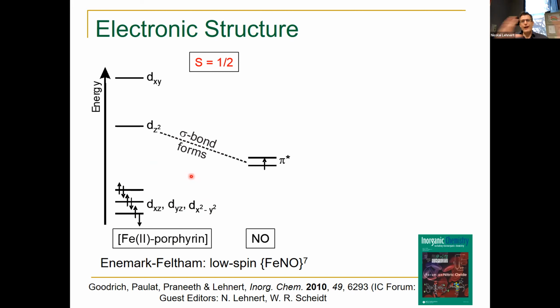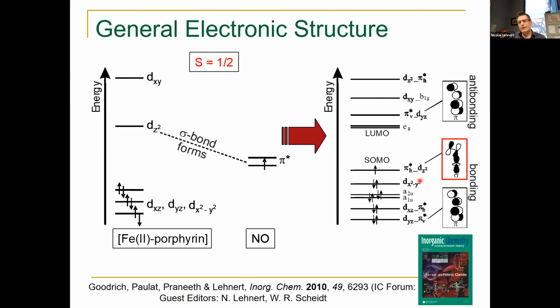So then, when we let these two fragments interact, we end up with this kind of a molecular orbital diagram. And the key orbital here is this interaction between the dz squared orbital of iron and this pi star orbital here of NO. This is a very covalent interaction. In the 5-coordinate complex, this is essentially 50-50 mixed. And this is really how this trans effect is communicated, right? When NO binds, it binds to the dz squared orbital and it pushes off the imidazole in order to strengthen this sigma bonding interaction. And that's what you can see in the vibrational data in the way that the force constants change. So using nuclear resonance vibrational spectroscopy, analyzing vibrations, analyzing bond strengths really allowed us to get to the heart of this electronic effect that activates soluble guanylate cyclase upon NO binding to the heme center.